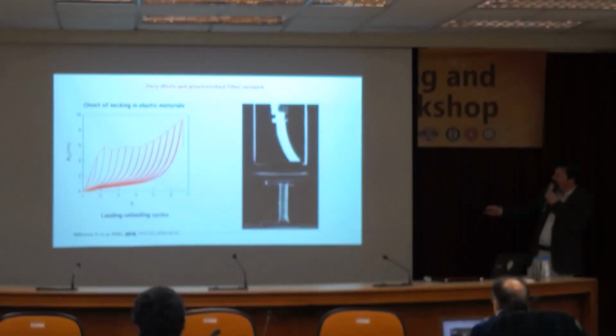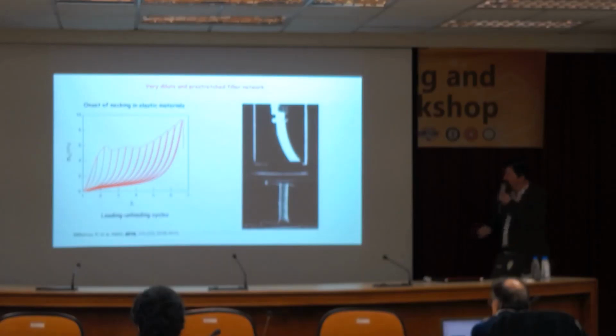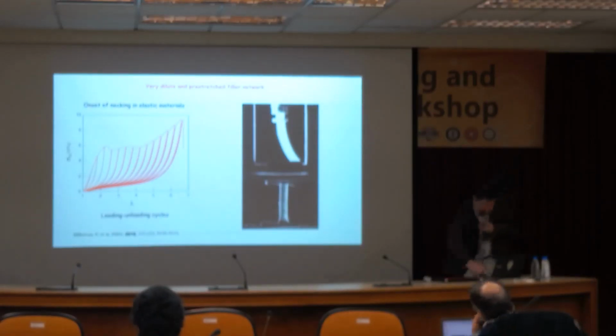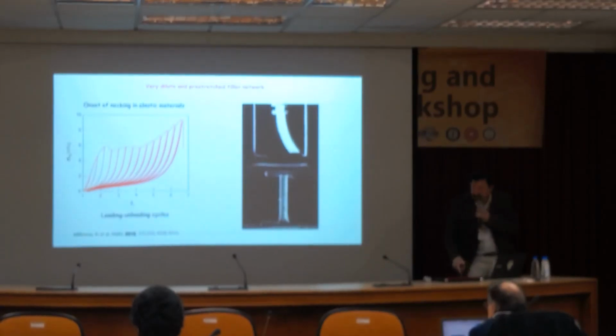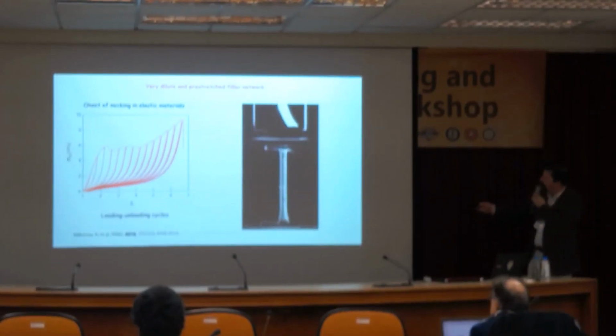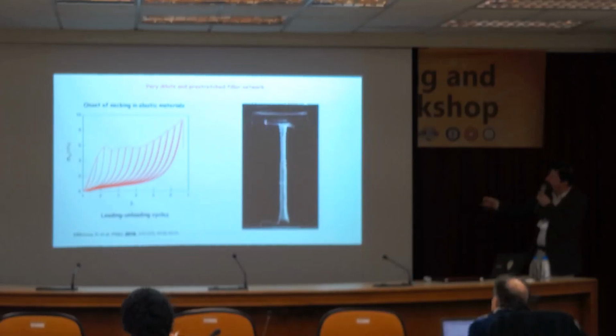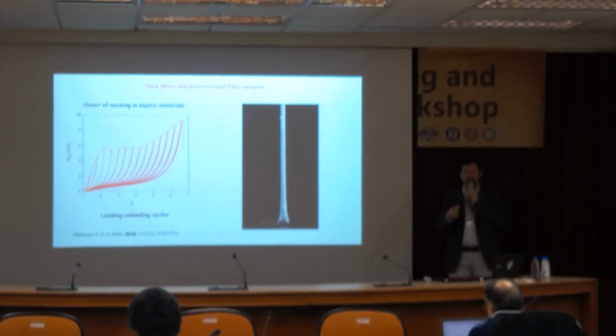And the reason of this yielding, which is not really a yielding in the plastic sense, is that you have a very strong softening. So I'm going to show you again a little movie. And in this movie, if you look up here, you'll see that there is a necking. Yeah, there is a necking process here. And the material splits into two zones, a highly stretched zone. Now it's completely highly stretched. And in the end, it will break. So we're in this regime here. This is loading and unloading, while this is continuous loading. But it looks like there is a kind of softening, a very strong softening. That was very peculiar, because normally you don't see this in elastic, really not in elastomer.